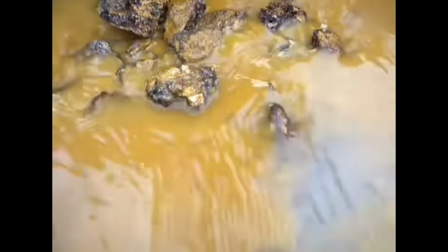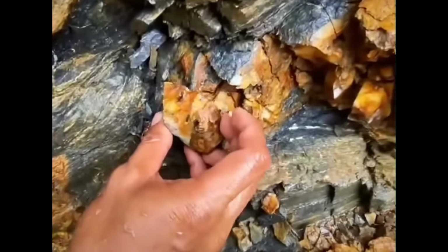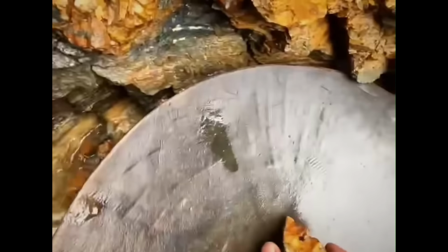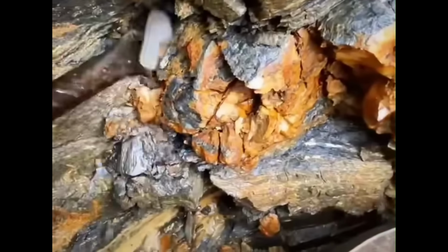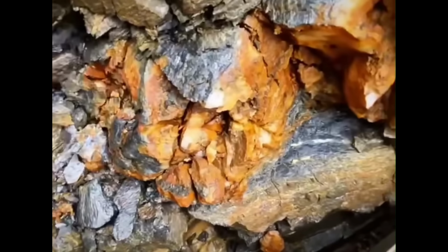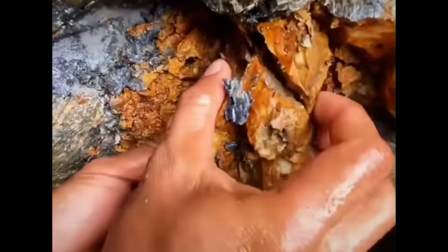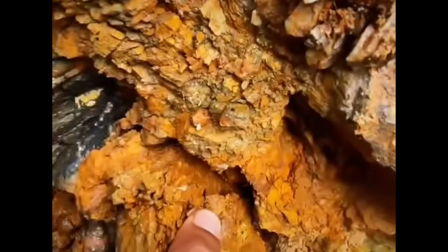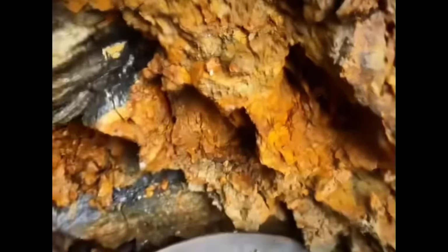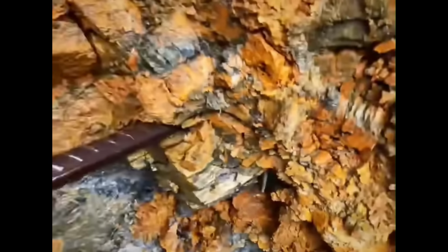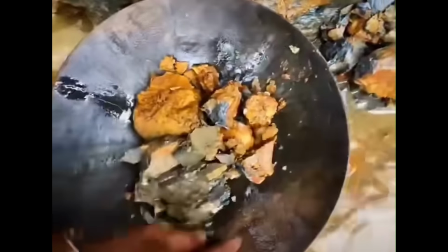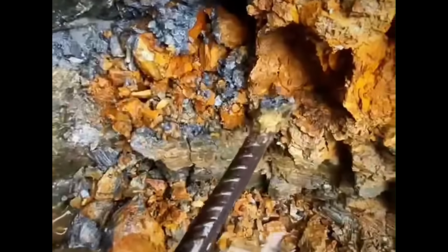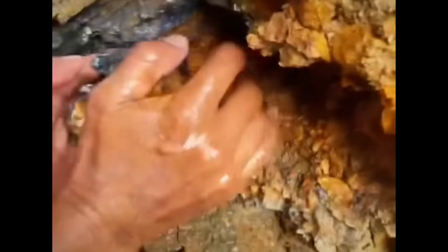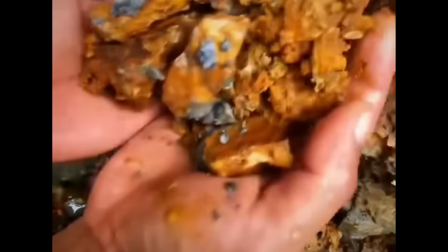Here's how it typically plays out. You crush a 500 g piece of stained quartz with some visible sulfides. The panned concentrate feels heavy, but the magnet pulls up nearly all of it, pure magnetite. That sample, despite its heft, is likely barren of gold. A second piece from the same vein yields a smaller, dull gray residue that doesn't respond to the magnet. A better target. Repanning that non-magnetic fraction slowly may reveal fine gold, often trapped beneath black sands or tucked in the pan's corners.